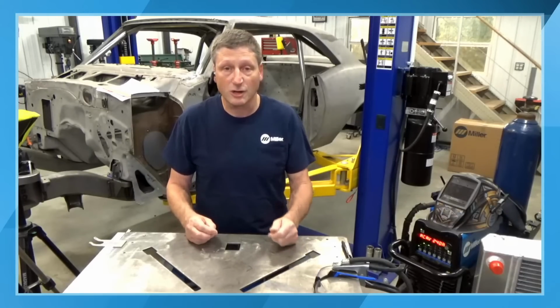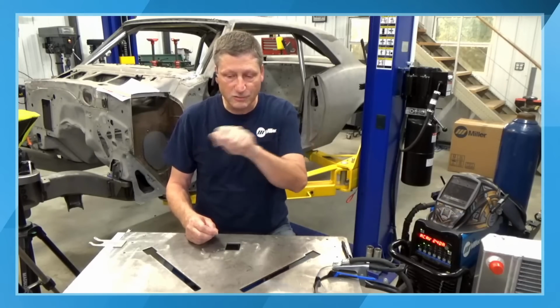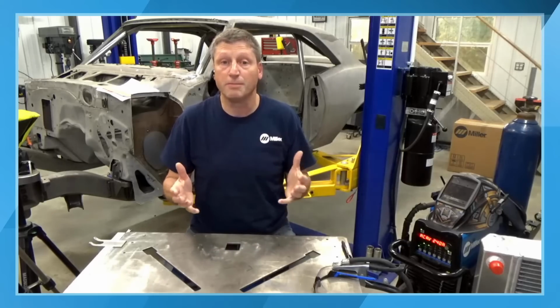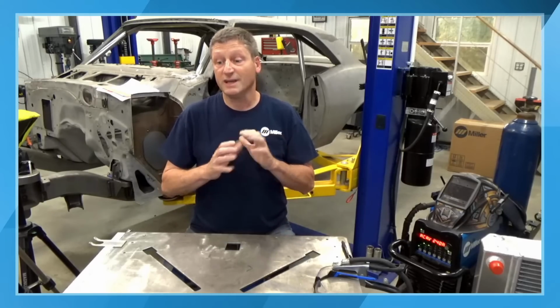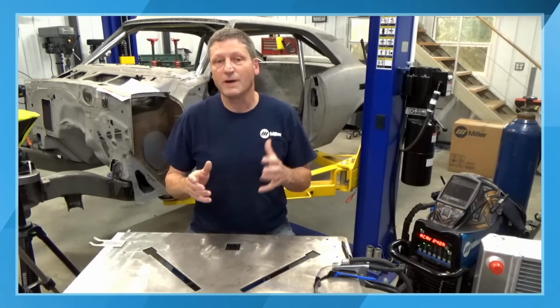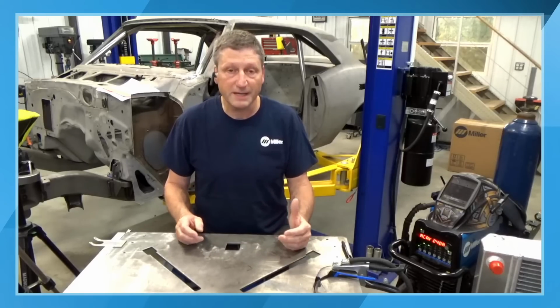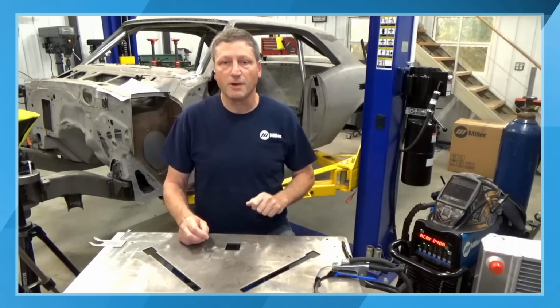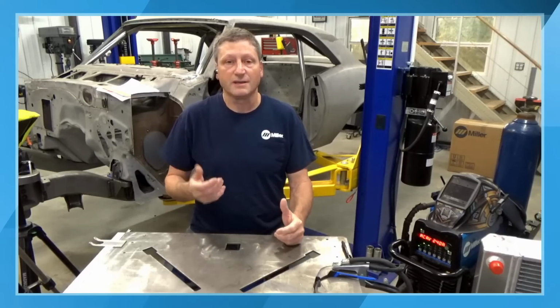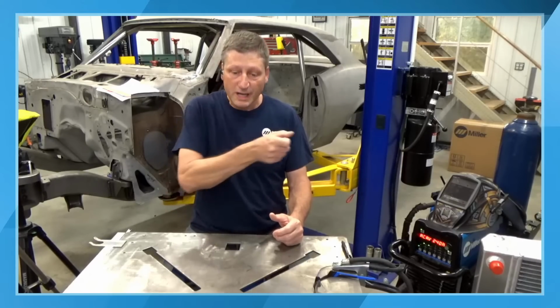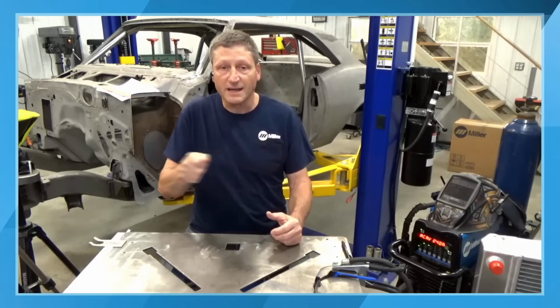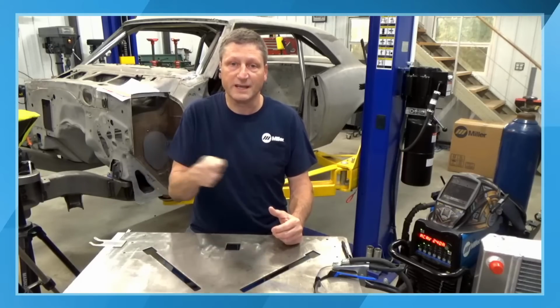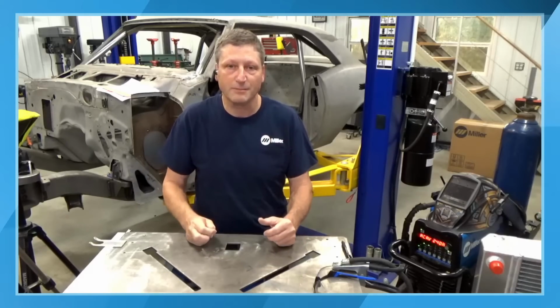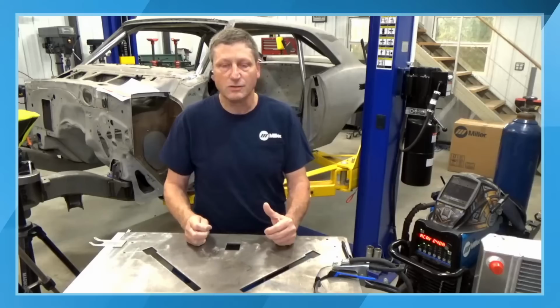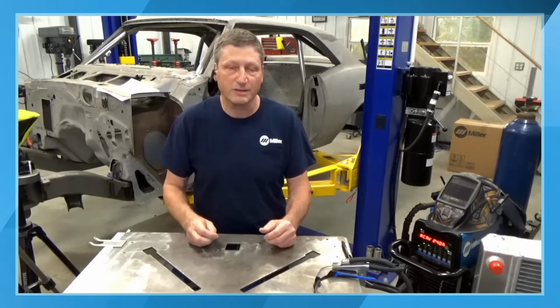Now, I use a couple different methods of doing it. I'll take a Sharpie marker and I'll just draw a couple lines where I'm going to be bending it. I don't necessarily anneal the whole sheet. I might anneal just where I'm going to be bending it. So I'll draw that on there, and then I'll take my torch and go along that line until the line disappears, and that's roughly the temperature level you need to anneal it so you can bend it easily.